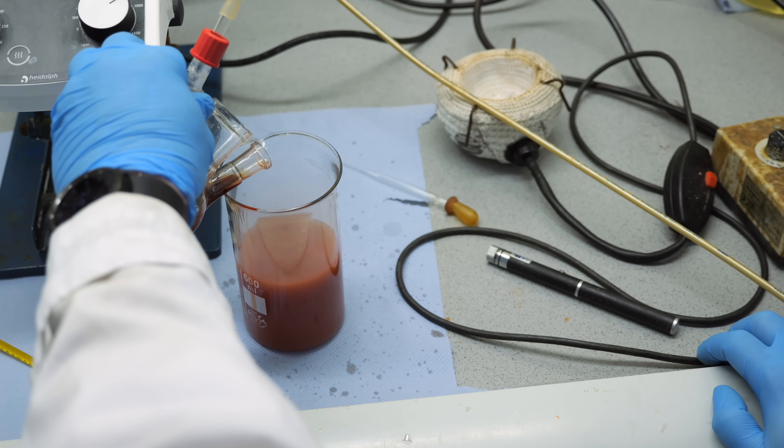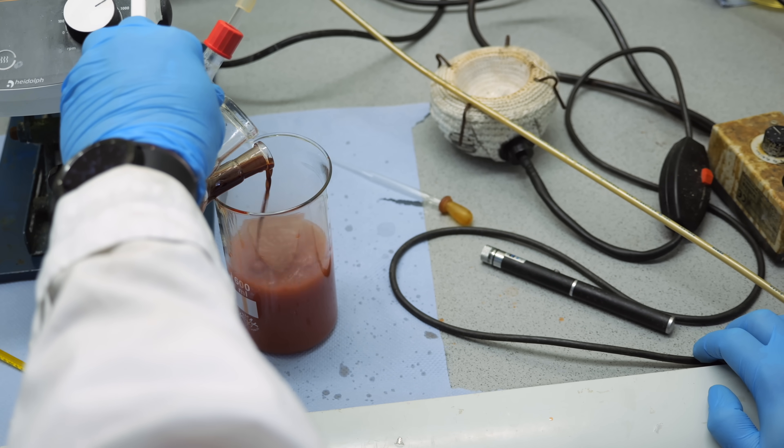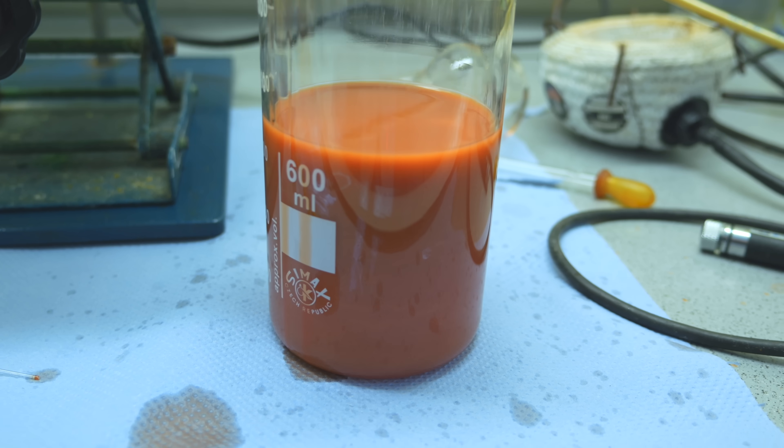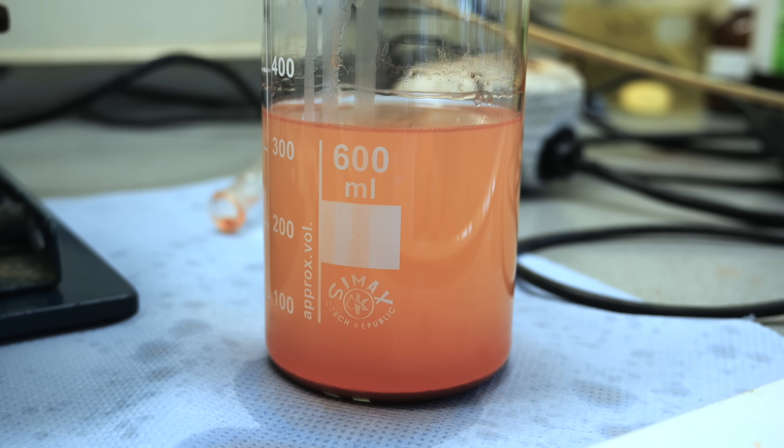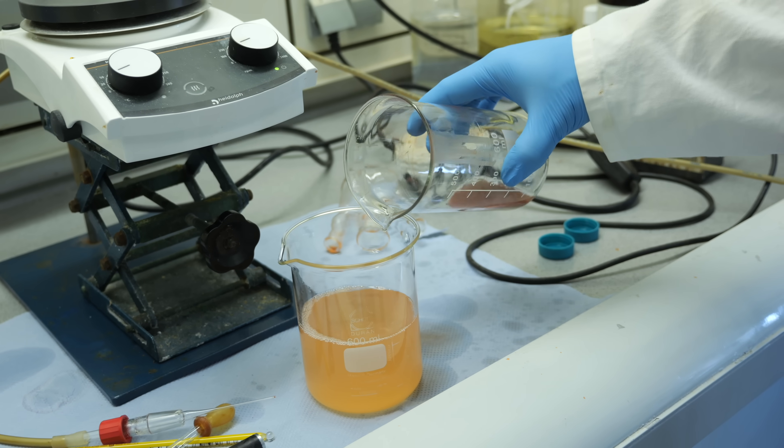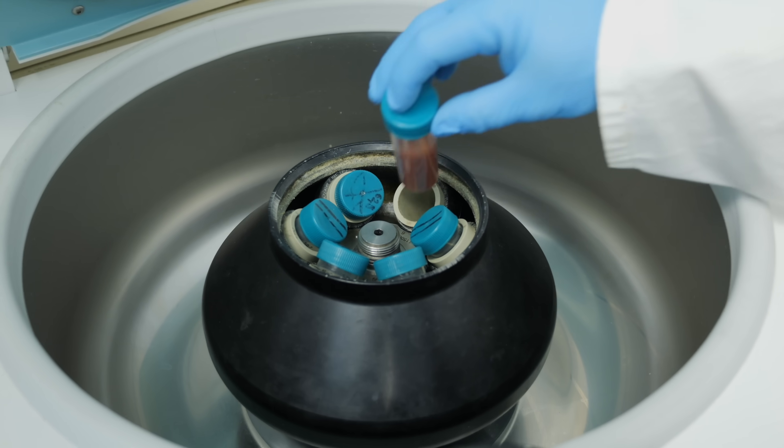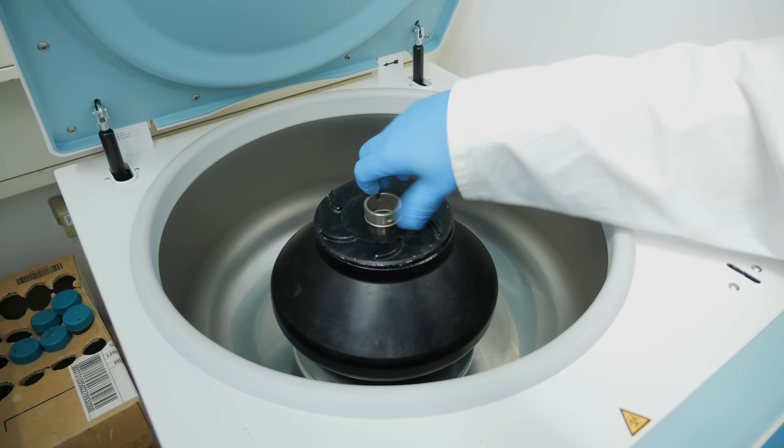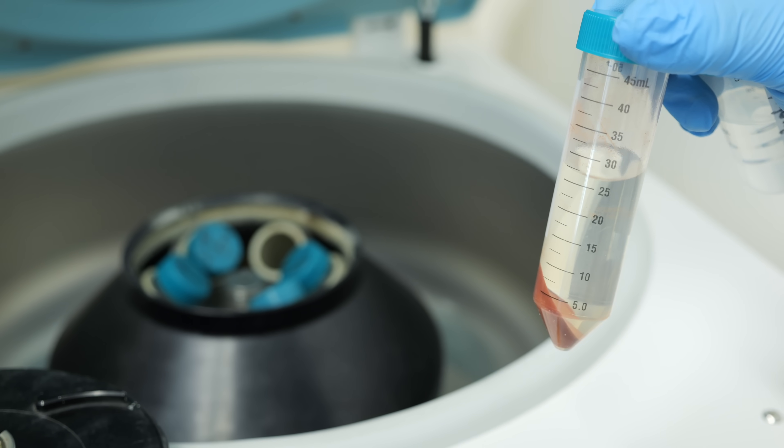So it's now time to separate them out from everything else that is floating around in this slurry, which includes pouring all of it into acetone first and letting the quantum dots precipitate or basically sink to the bottom. This allows us to pour off the remaining liquids, then we can centrifuge the remainder, we can pour off the liquids again, etc. And in the end, we have just the quantum dots. How cool is that?